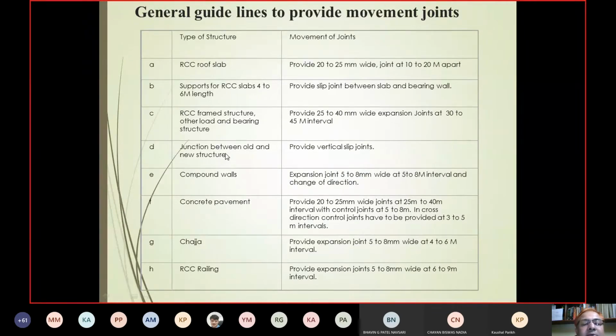In the junction between old and new structure, provide a vertical slip joint. In compound wall, expansion joint 5 to 8 mm wide at 5 to 8 meter interval. I see lots of compound walls which have failed due to this reason. It is tilting. Concrete pavement: provide 20 to 25 mm joints at 25 to 40 meter interval, and control joints at 5 to 8 meter, in the cross direction at 3 to 5 meter interval.